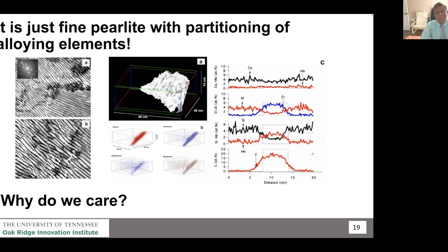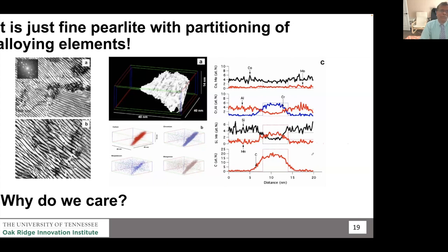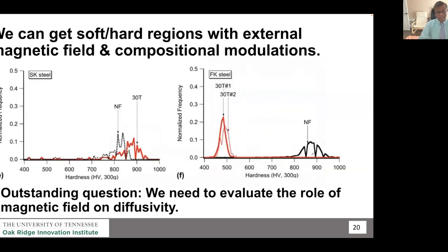This super bainite is not supposed to transform to pearlite under normal continuous cooling conditions. Indeed, when you go into transmission electron microscopy, you can see fine pearlite. What is so surprising is that even though we are cooling at one degree centigrade per second, the alloying elements actually partition between cementite and ferrite during transformation. This connects back to Hillert's classic paper on pearlitic microstructure and substitutional redistribution using it as a time-temperature recorder for steels — very important to understand substitutional motions during pearlitic transformation.